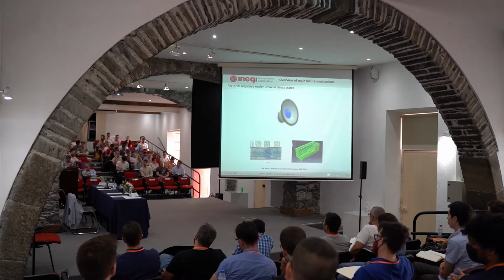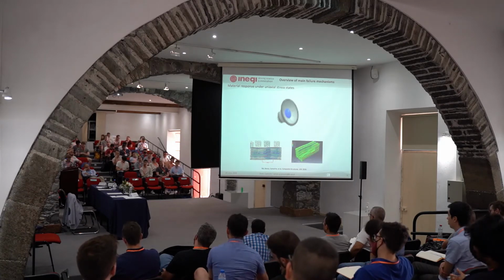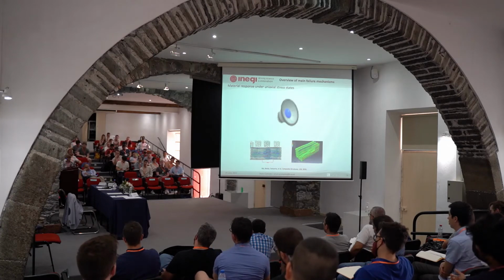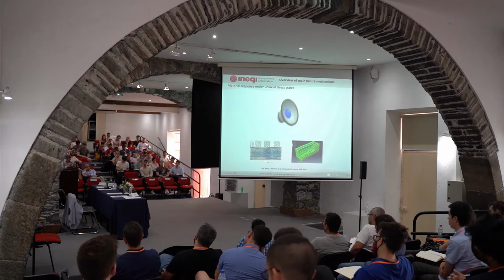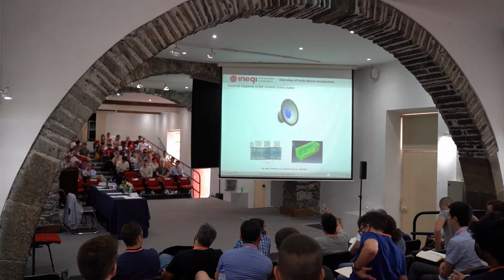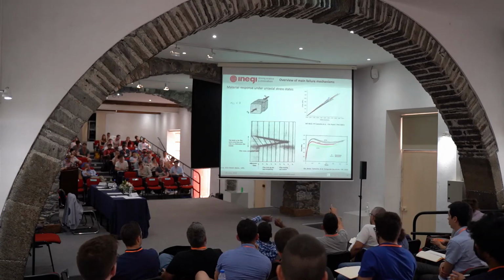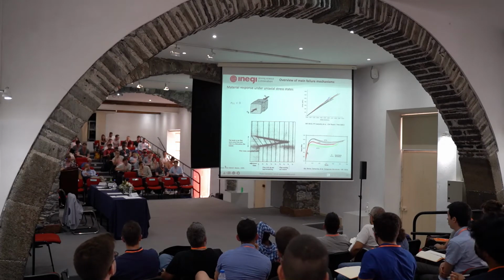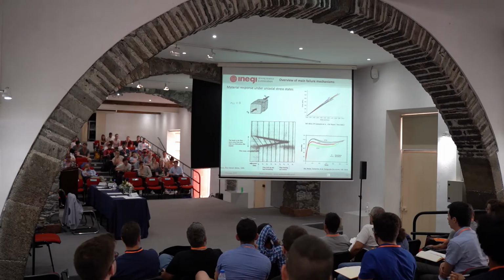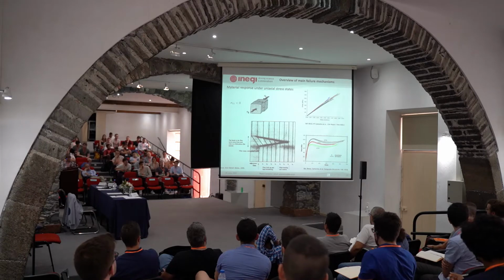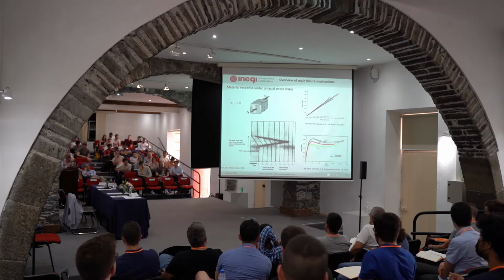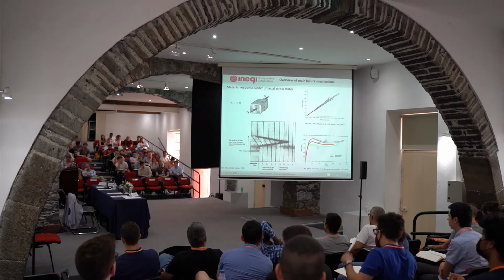Okay. So the problem in terms of homogenizing and getting properties is when you have damage, because it's not trivial to homogenize in the presence of this damage. Okay. Maybe you can show the previous page, the data. Yeah. This one here. Actually, bottom of the. This one. Yeah. Okay. No, this is not for composite. This is for the neat resin. So these were tests that were conducted in... So these are shear tests in neat resin at different strain rates. And we are showing data at different temperatures.